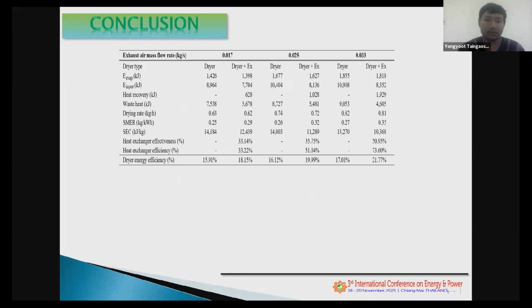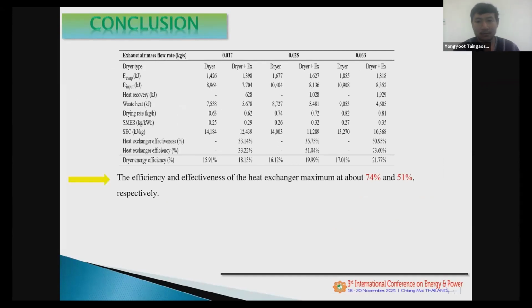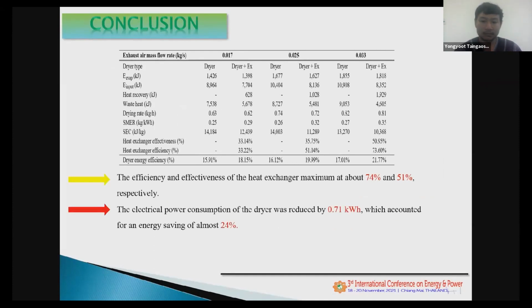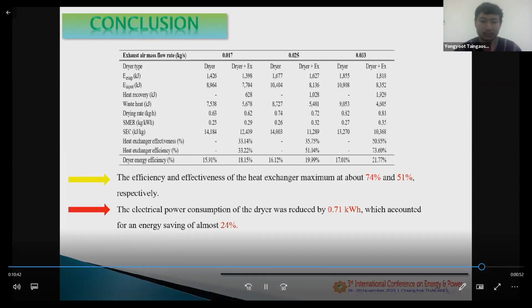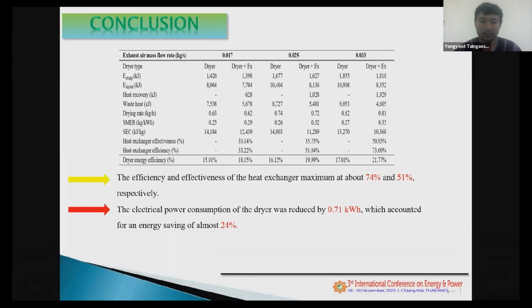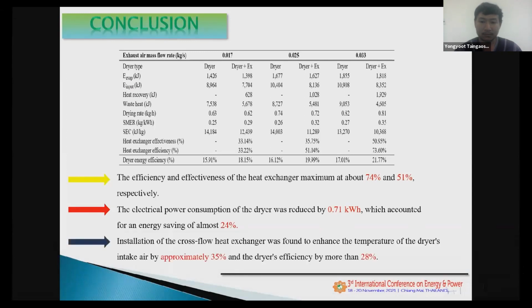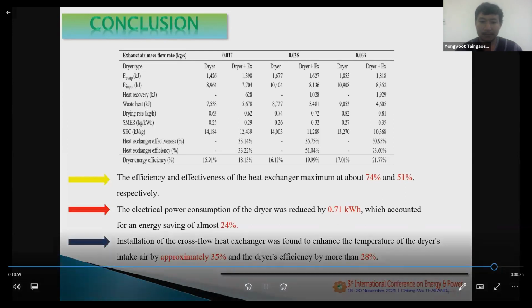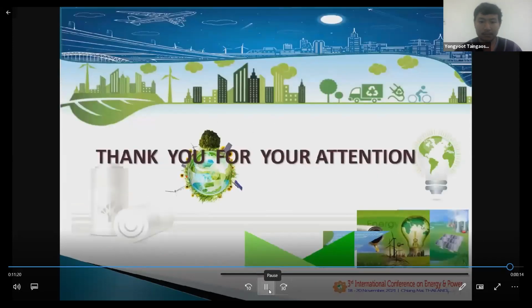So the conclusion of this research, you can see on the table: the efficiency and effectiveness of the heat exchanger were measured at about 74% and 51% respectively. The electrical power consumption of the dryer was reduced by 0.71 kilowatt-hour, which accounts for an energy saving of almost 24%. Installation of the cross-flow heat exchanger was found to enhance the temperature of the dryer intake air by approximately 35% and the dryer efficiency by more than 28%. Thank you for your attention.